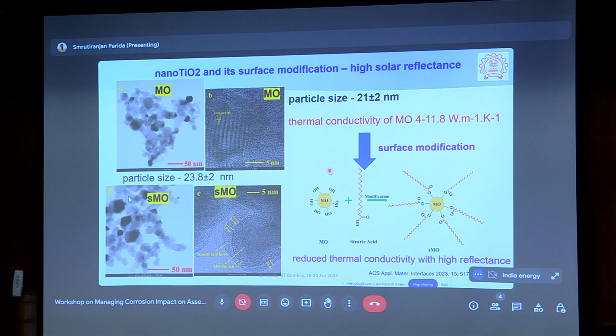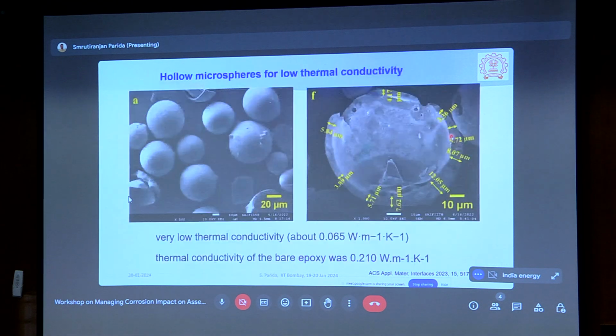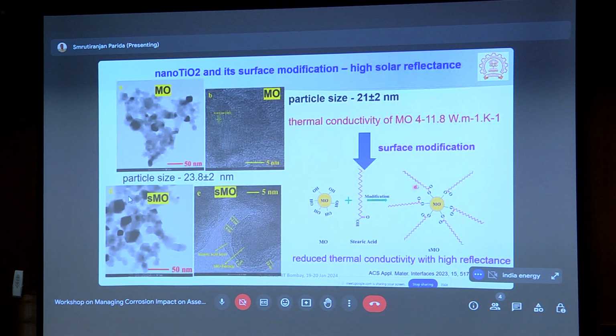So one of the demerits of adding this material directly to the coating is that TiO2 has a very high thermal conductivity, if you compare with our cenosphere or microsphere or epoxy. So it is very high thermal conductivity. On one hand, we can increase the reflectance by adding this MO. I will call TiO2 MO throughout. But then it increases thermal conductivity. So it doesn't support the next component of our